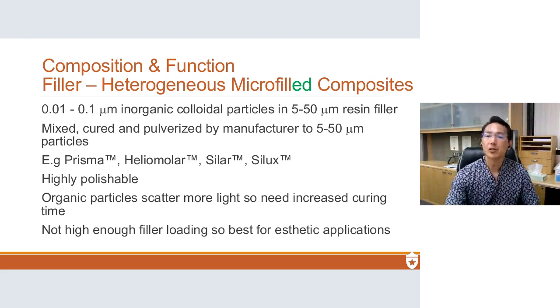So microfill composites basically have nanoparticles embedded in 5 to 50 micron resin particles. I told you about this process. Some examples of this, the most famous is Heliomolar, which is still used. They're highly polishable. The organic particles still do scatter light, and so it actually has increased curing time. And the filler loading is still not up to par for posterior applications. It's still best for aesthetic applications.